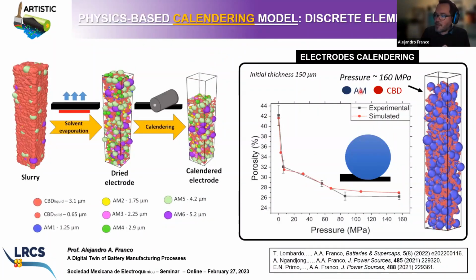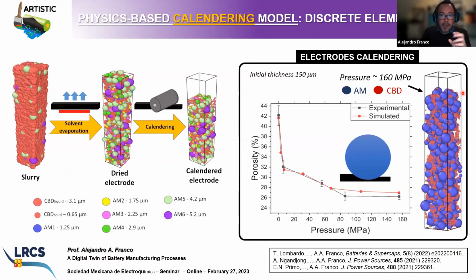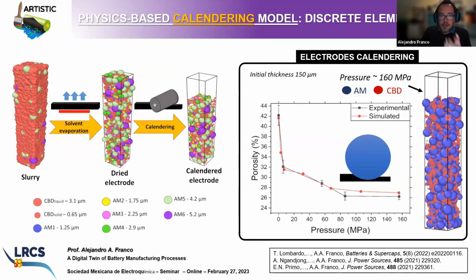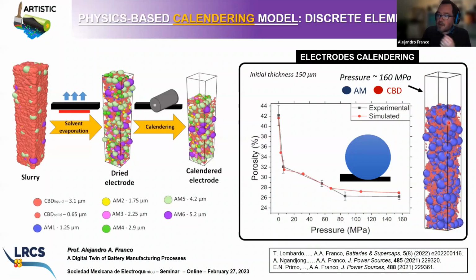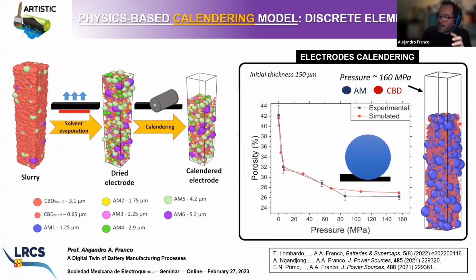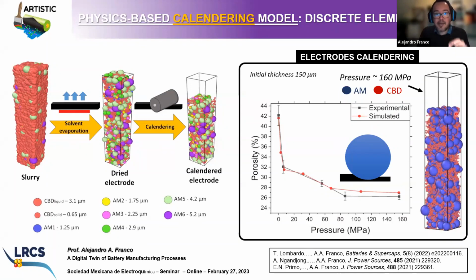I'm going to play the video again on the electrode microstructure evolution. In blue, you see the active material particles, in red, the CBD particles. And you see that when you compress the electrode, there is a plastic deformation, but also there is a little bit of elastic recovery. This is a phenomenon called spring back in the battery manufacturing field, which is widely known, in particular in industry, and it's very difficult to optimize.